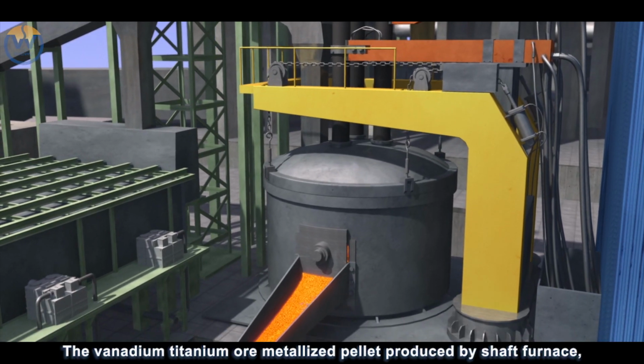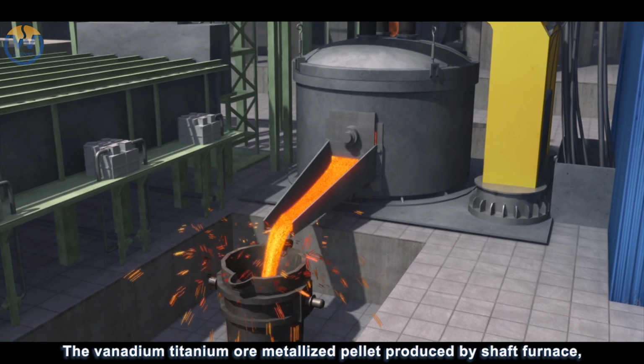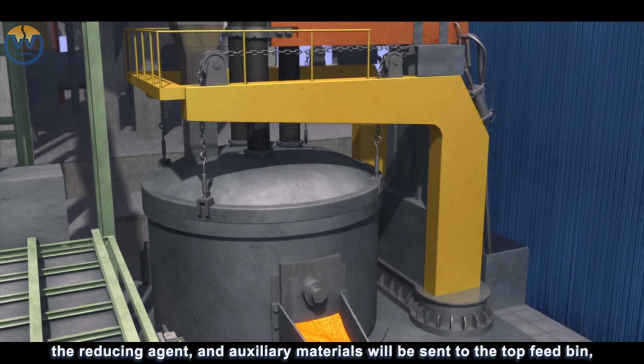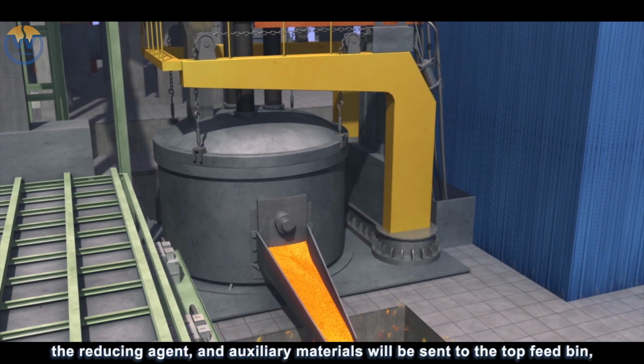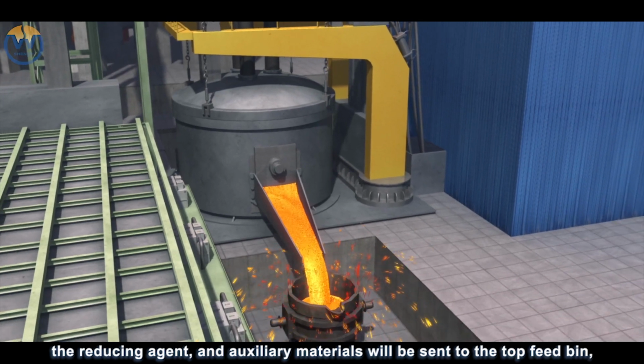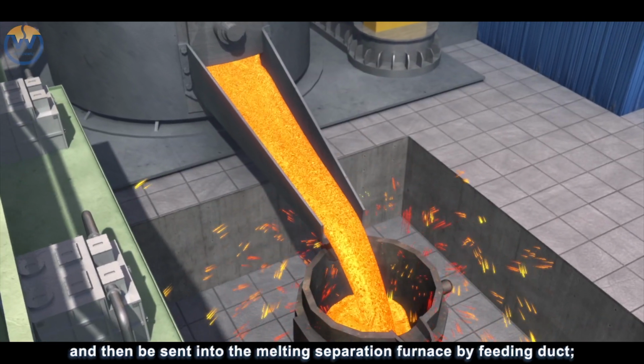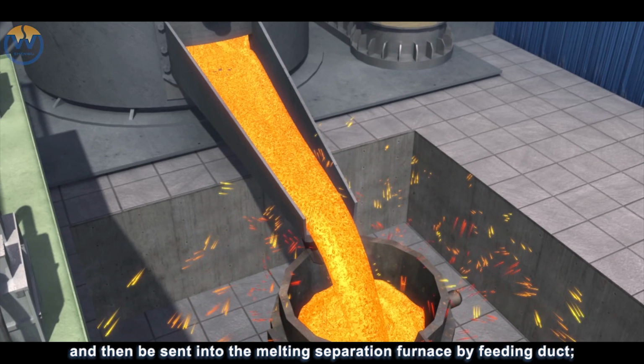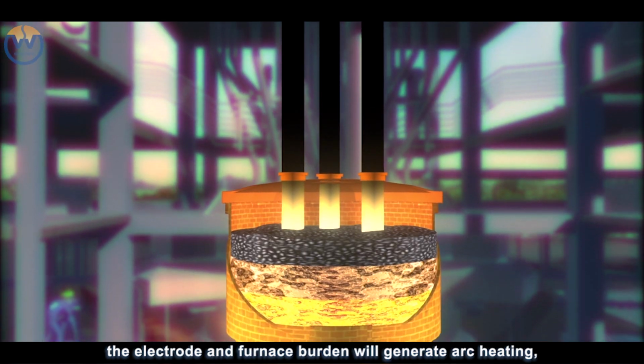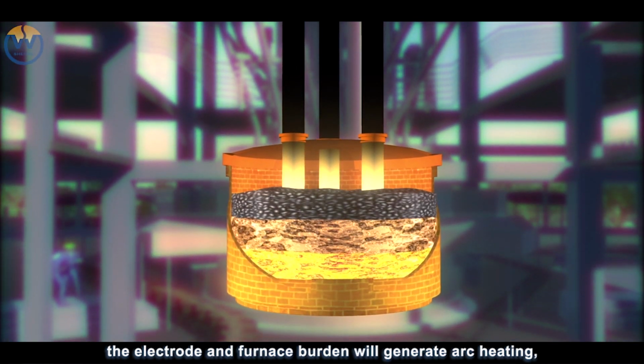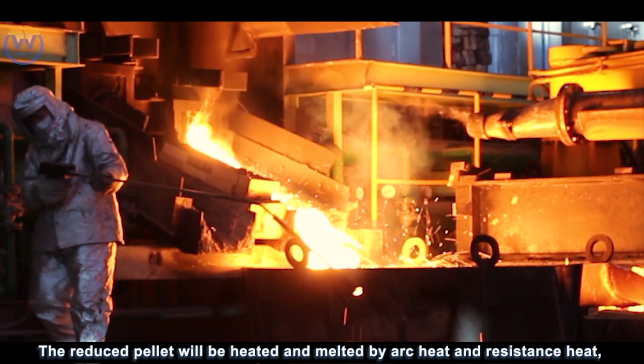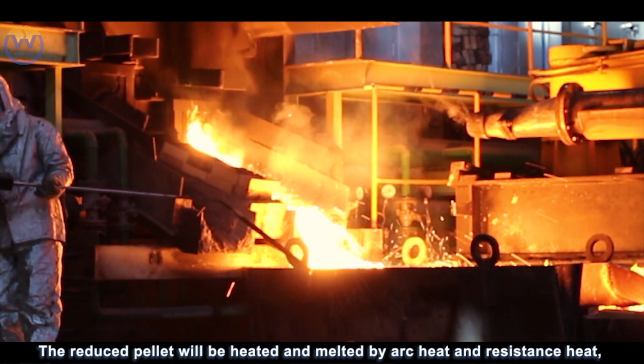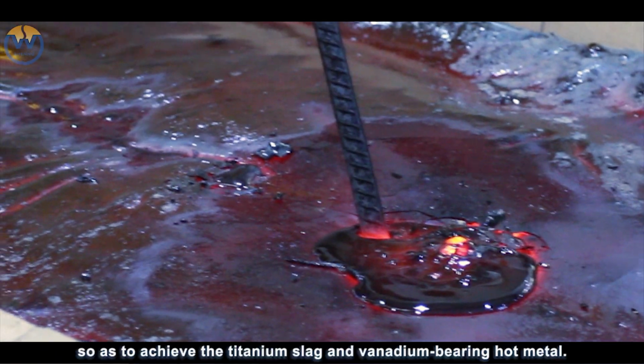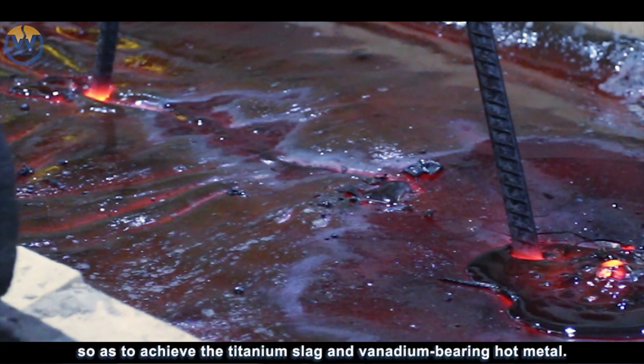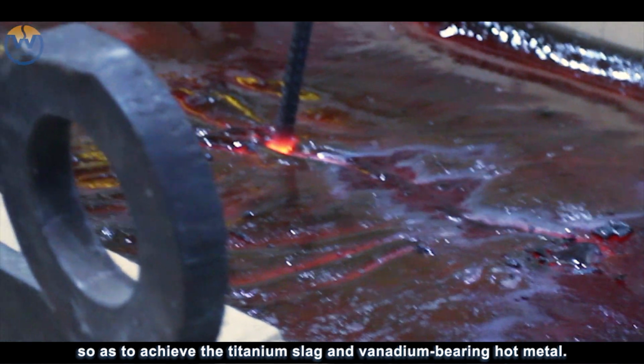The vanadium titanium ore metallized pellet produced by shaft furnace, the reducing agent, and auxiliary materials will be sent to the top feed bin and then be sent into the melting separation furnace by feeding duct. The electrode and furnace burden will generate arc heating, and the heat will be transmitted to the furnace chamber. The reduced pellet will be heated and melted by arc heat and resistance heat so as to achieve the titanium slag and vanadium bearing hot metal.